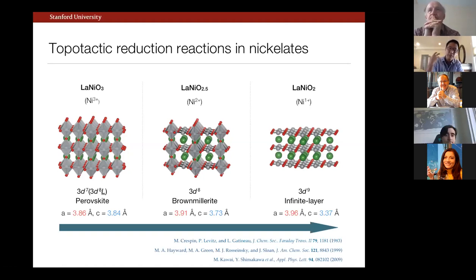And so, for example, here's another dilemma. It's not easy to do, but there are a few groups that can do high pressure bulk single crystal synthesis. And I think the dilemma there is, why don't you reduce that? There's nothing to break the degeneracy. I can pull out this plane, this plane, this plane. And so you make, at best, a polycrystalline kind of mess. And so I think that's the trade-off for the thin film case.